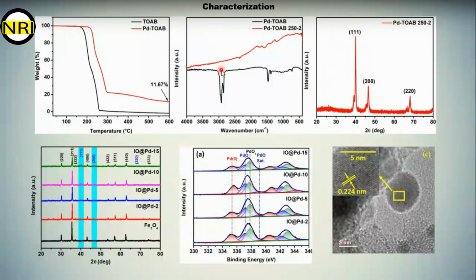To know whether it is palladium or not, I measured XRD, and we can see that after heating at 250 degrees C, only the FCC cubic lattice structure of palladium is present, and no organic residues are there in the sample. After confirming this, I loaded this palladium TOABr in different weight percentages on the Fe3O4 and heated at 250 degrees C for 2 hours, and then characterized well with XRD, XPS, HRTEM, SEM and all. So this is the XRD pattern of the heated sample.